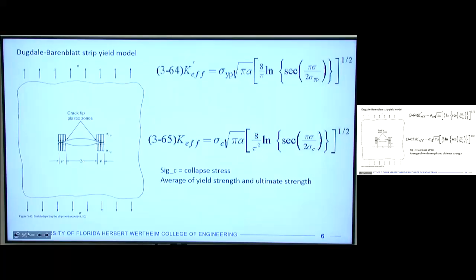And so these researchers came up with a model that is represented here. So here's the crack. It has all the same dimensions that we had before. So we had a, we have stress pulling on it. But rather than have a circle and try to approximate what's happening there, they call these plastic zones basically strips that are acting with stresses perpendicular to the orientation of the crack. And at the crack tip, they said, okay, if we know that this is going to basically be yielding, we'll just assign the yield stress, so it says sigma yp there if it's too small to read, that the yield stress is acting at those crack tips in this kind of geometry.